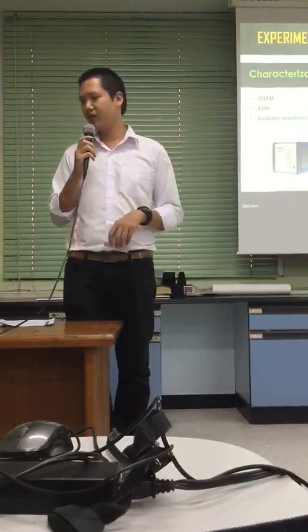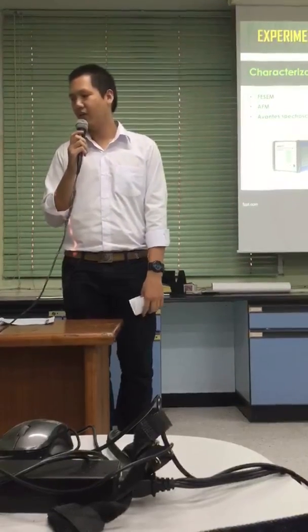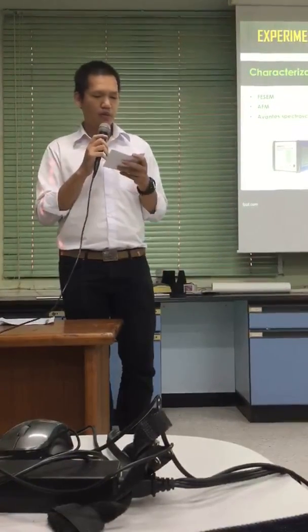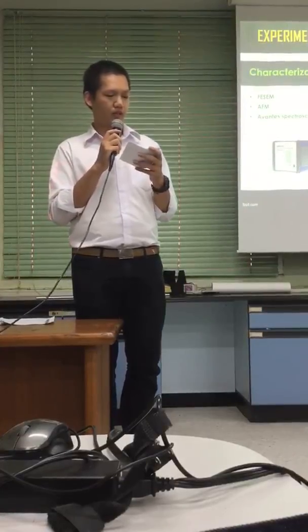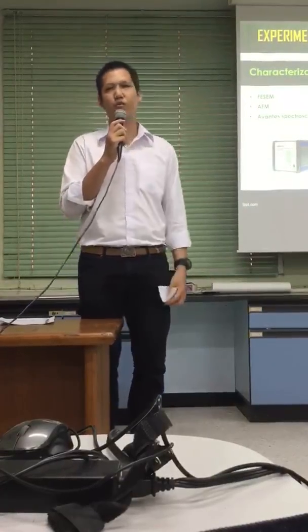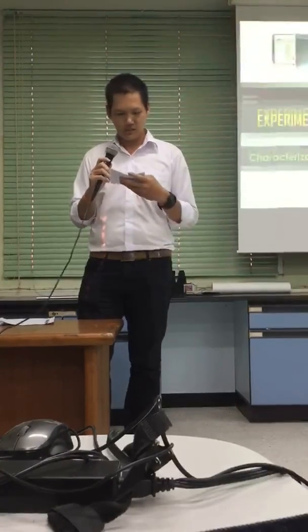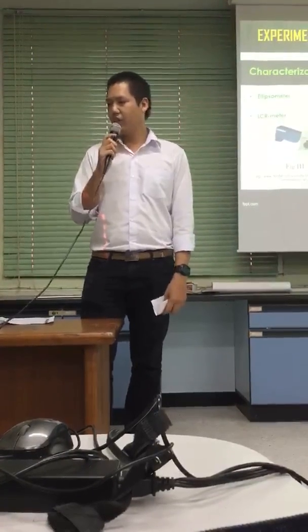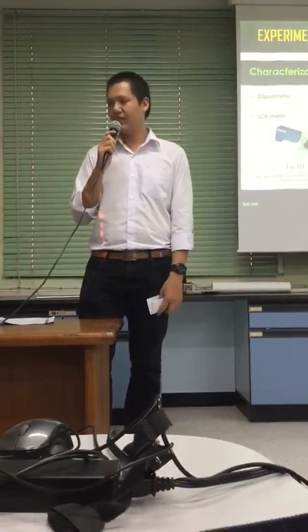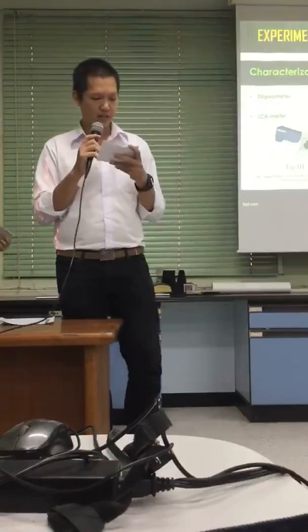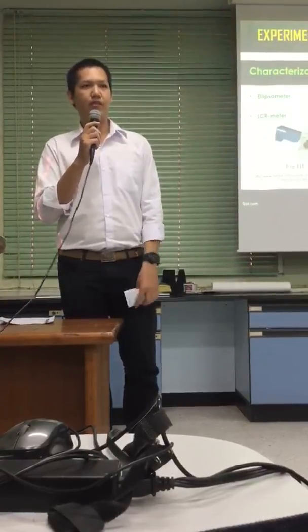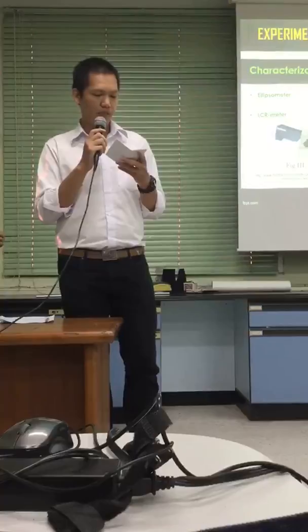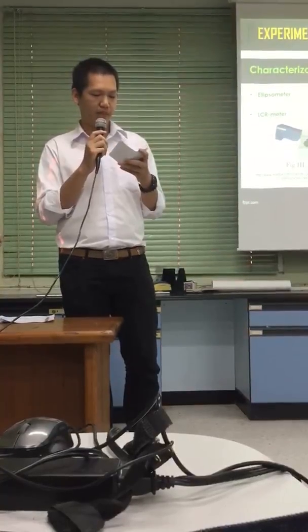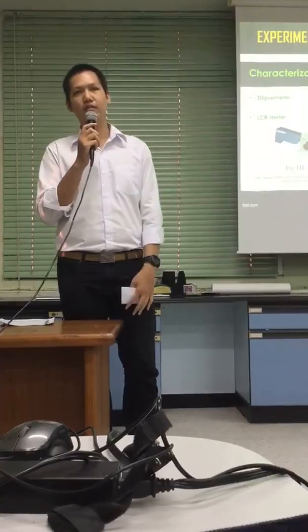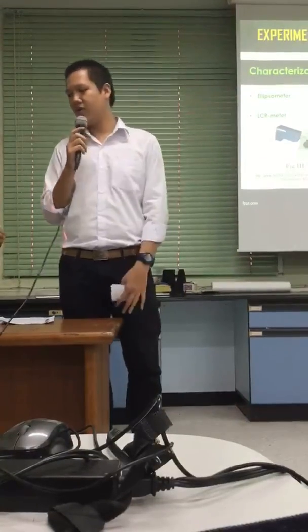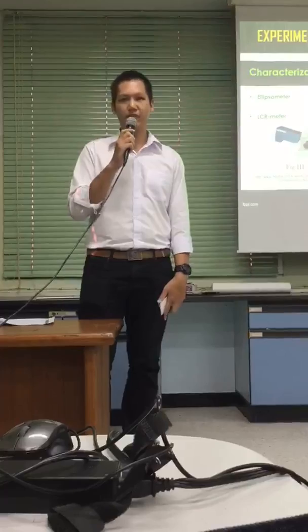UV-vis spectroscopy was used to measure the optical transmittance and band gap with wavelength range of 300 to 900 nanometers at room temperature. Ellipsometer was used for measurement of thickness, refractive index, and extinction coefficient with incident angle of 70 degrees. Spectral wavelength was from 250 to 1800 nanometers with step of 5 nanometers. LCR meter was used to measure resistivity.